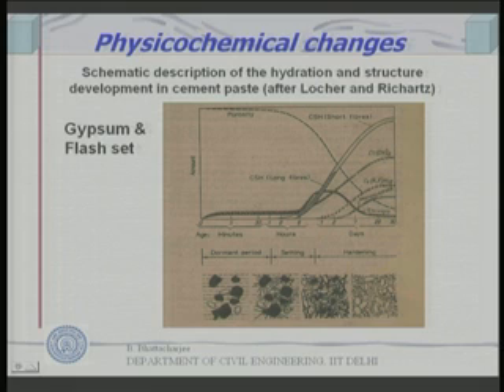So, this is how the physical changes take place. This is the dormant period, this is the situation where setting is taking place, that is final setting, and for hardening this is the scenario, and then after 90 days or so, you will have a firm solid structure. Now, you can see that this is ettringite, mentioned here. So, initially ettringite is formed during the dormant period.